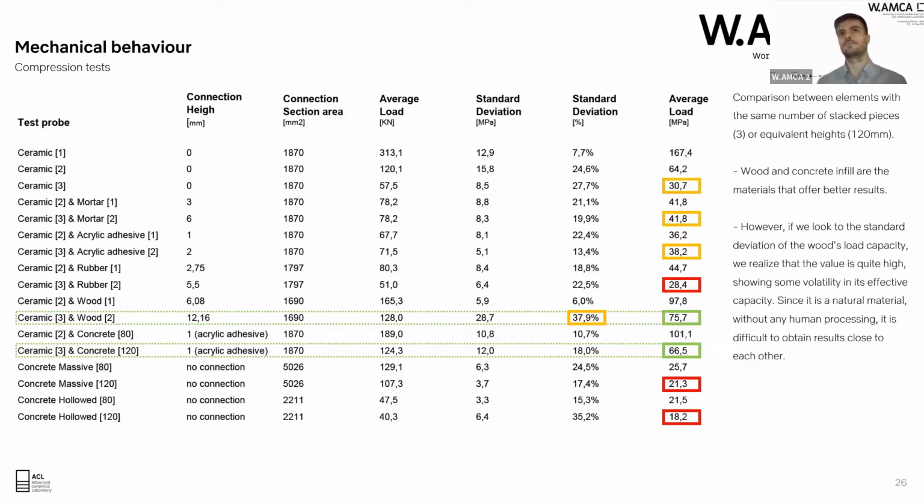The critical compressive loading drops so much just by the way it behaves. It's exponential. Even in concrete you have that. But the main problem is that the ceramic pieces are not completely flat, so when we stack two or three, they crack.